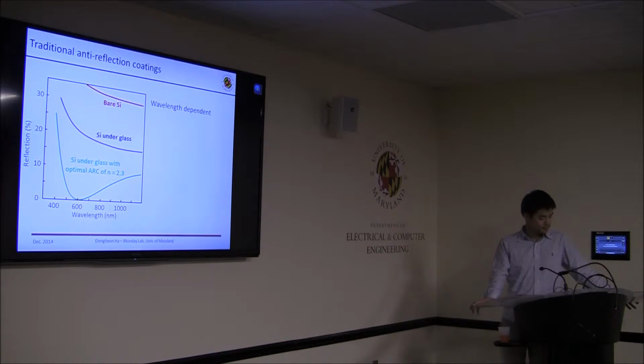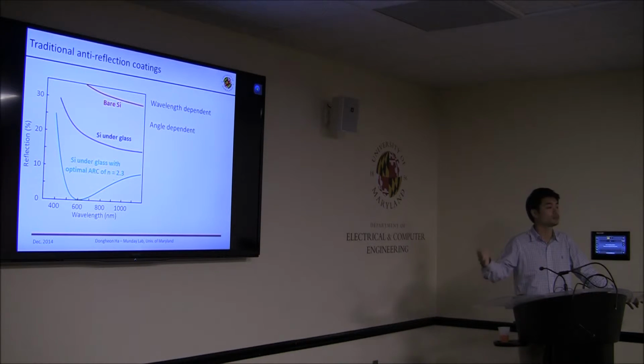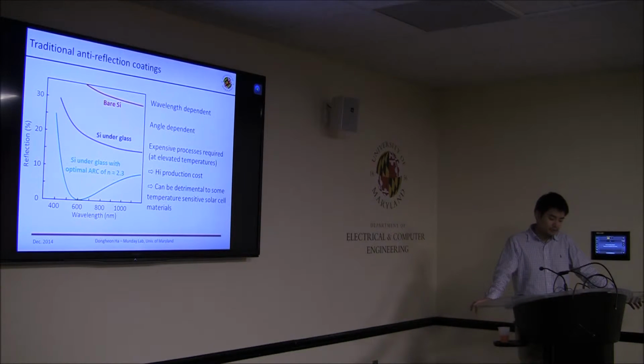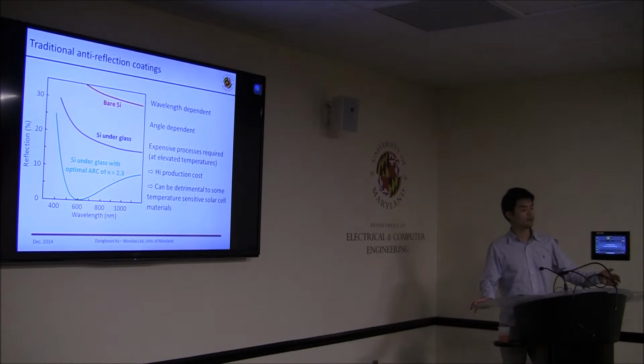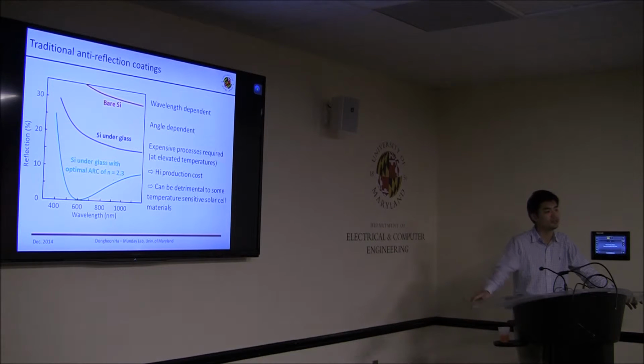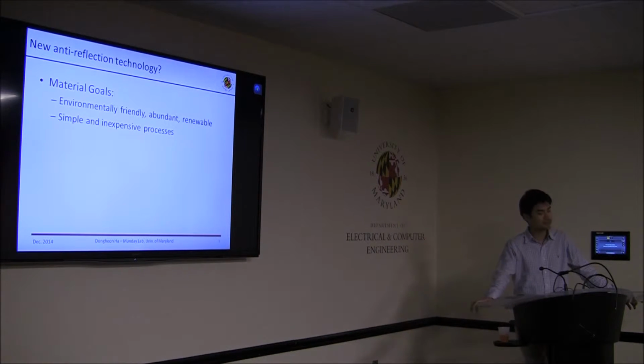However, there are also some disadvantages. It is obvious that we cannot avoid wavelength-dependent behavior. The other thing we can see here is that we have angle-dependent behavior because the optimal condition is valid for some specific incident angle. And one of the most critical disadvantages of this method is that we need very expensive and high temperature fabrication processes to make such layers. Because those layers require high temperature fabrication, they could be detrimental to some temperature sensitive solar cells. So, okay, we are going to make new anti-reflection coatings to address the aforementioned shortcomings.